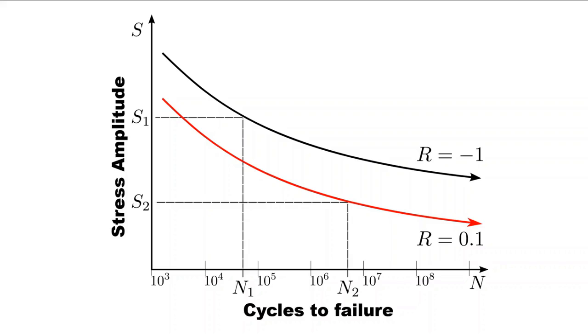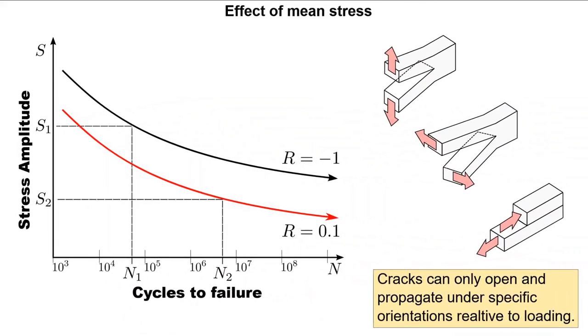For the same number of cycles, a material will withstand a higher stress amplitude at R equals -1 versus R equals 0.1. This is because of the mean stress effect. If the mean stress is 0, then the material spends half of every cycle in a condition where the crack does not open. Cracks only propagate in tension, as shown on the top, or some of the more complicated modes, as I've shown below this. We'll get into this further when we discuss fracture. This is why the results from a Wohler test are conservative. Only half of the material is in tension at any given point in time, meaning that an SN curve derived from Wohler results will predict higher stresses to failure for a given number of cycles as compared to an equivalent uniaxial stress state.